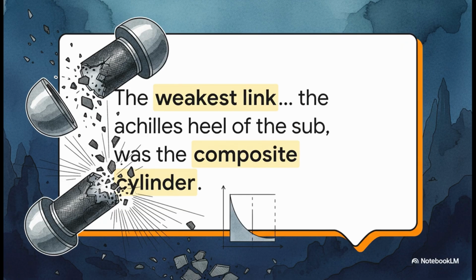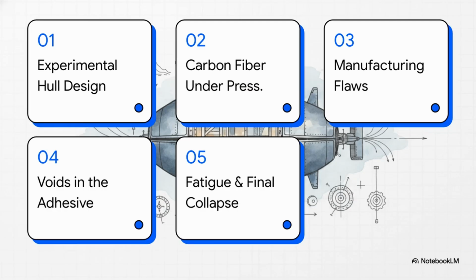He pointed out that while the titanium end cap survived totally intact, the composite cylinder was reduced to small pieces. It just highlights the fact that, traditionally, you simply don't use composites for vessels experiencing massive external compression. So, here is our roadmap for this explainer. We'll start with the experimental hull design, then move to carbon fiber under pressure, look at manufacturing flaws, examine voids in the adhesive, and finally, piece together the fatigue and final collapse.